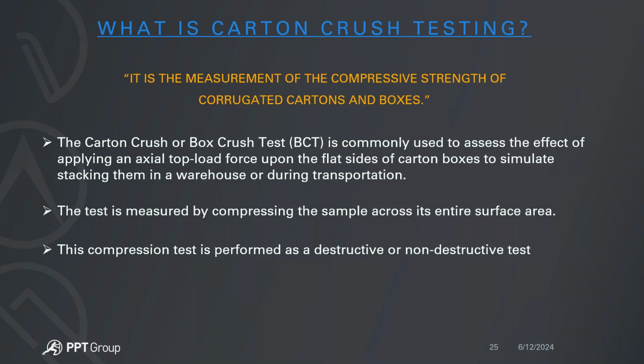Again, the test is measured by compressing the sample across its entire surface area, and this compression test is performed as a destructive or a non-destructive test. In a typical destructive test, you would either crush it to a known deflection, apply a known force, or apply force until the sample fails. But usually in non-destructive testing, especially if you're doing 100% testing, you're making these cartons and you want to know if they meet a certain criteria of, say, 200 pounds of axial force or axial load. So once the sample is put in the tester, you apply a known force, 200 pounds, 100 pounds. As long as the sample meets that minimum criteria without failing, it's a good sample. You just pack them for shipping.